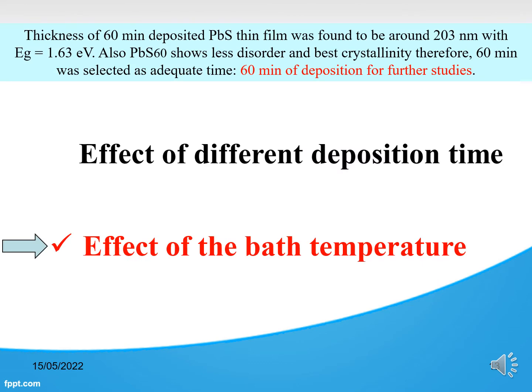The thickness of the 60 minute deposited PbS thin film was found to be around 203 nanometers with a band gap energy of 1.63 electron volt. Also, PbS 60 shows the least disorder and best crystallinity. Therefore, 60 minutes was selected as the adequate time of deposition for further studies.